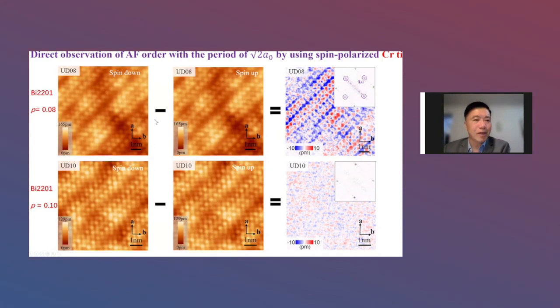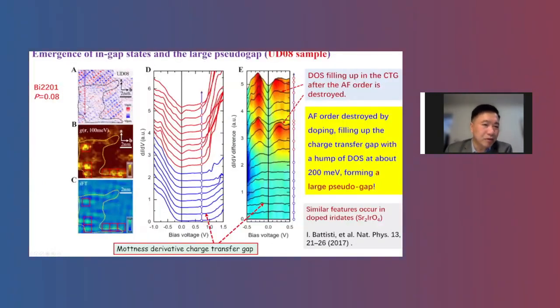Then we take the 8% doping sample, we measure tunneling spectrum from the area with anti-ferromagnetic order to the area without. Then you can see that the tunneling spectrum changes from a so-called charge transfer gap region. So the gap is about 1.5 eV, which is almost featureless in the region with anti-ferromagnetic order. However, when you move into the region without this order, then you will see that some kind of density of states piles up in a very wide energy area. And the Fermi energy is pinned here, okay?